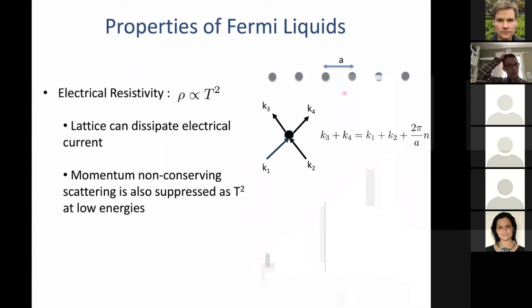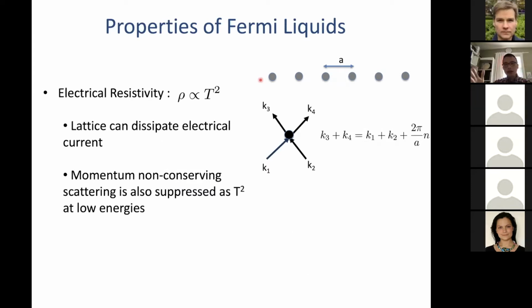And then another thing that people measure is transport. So you apply voltage. So you run electric current through the sample, and you ask how much voltage drop there is in the sample, and that is electric resistivity. And in metals, because of this periodic structure made of ions, the continuous translational symmetry is broken. So therefore, momentum is not conserved. For example, as electrons scatter, the total momentum can change by this momentum associated with the periodic structure, right? If a is the periodicity, then 1 over a is basically the momentum that can be provided by this periodic structure. And because of this momentum non-conserving scattering, you can have a resistivity in the system.